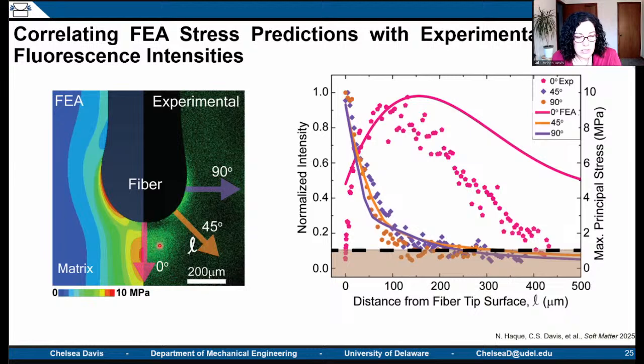And we believe that this is due to the fact that we're using a perfectly elastic mesh for our FEA, and we're not incorporating any damage or allowing any damage or chain scission events, which are almost certainly happening at these high loadings within our polymer network. So we're working to see if we can incorporate the idea of damage and stress redistribution as a function of damage within our network.